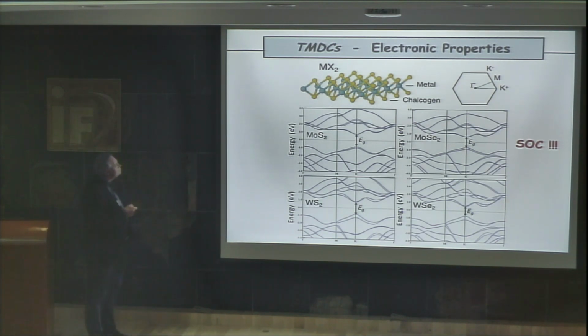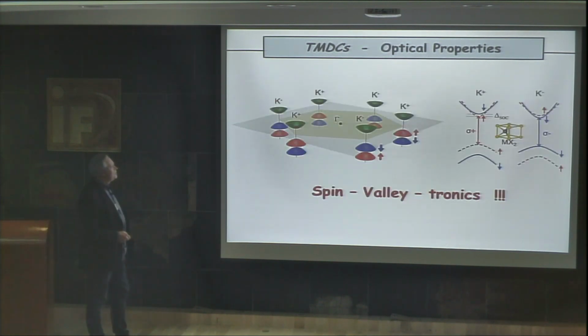And in this material, since you can in fact have very heavy elements like tungsten, the spin-orbit coupling becomes very important as well. So in this situation you see, for example, a splitting of the valence band, which is of the order of a few hundreds of milli-electron volts, and about tens for the conduction band. So this also introduces some modification of the electronic properties compared to other 2D systems. And this is very interesting for optoelectronics, again, because in this system you have a broken inversion symmetry in the case of a monolayer.